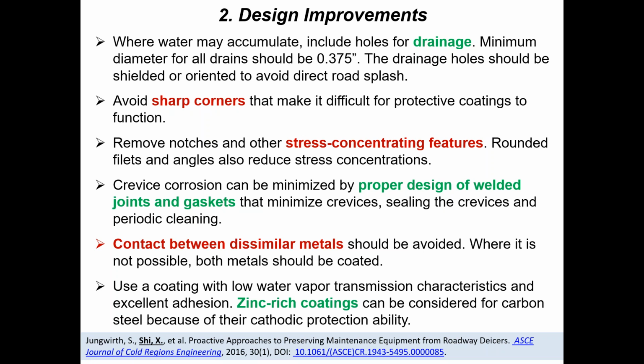But anyways, the galvanic corrosion is a significant risk. Now, the use of some of the coatings would be helpful, especially the so-called active coatings such as zinc-rich primer. Now, this is actually flipping the theory of cathodic protection to our benefit. Basically, because the zinc in the coating is a sacrificial anode, it tends to oxidize easier than steel. So it will sacrifice itself and pump a lot of electrons towards the steel, making the steel corrosion resistant.